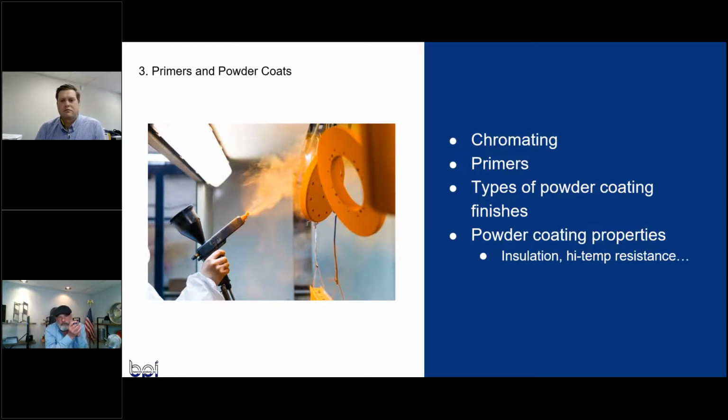And it's, you know, 2 feet square, 8 inches deep. More than likely, if it's powder coated, it's powder coated with acrylic because it can stand the heat. Then there are hybrids. This is a blend of an epoxy and a polyester. If you have a powder coated desk in your office, that's hybrid powder. That's what the metal office furniture industry uses.